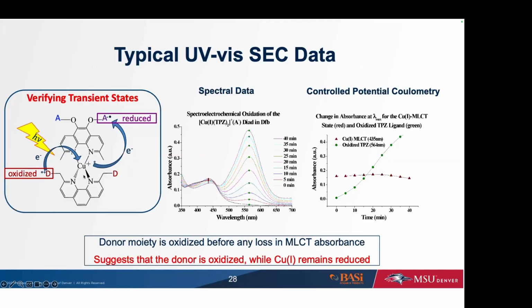So we were trying to determine with our spectroelectrochemistry, are we able to oxidize the donor before any loss of the metal to ligand charge transfer state, and to make sure that our copper is staying in the copper 1 state and not getting oxidized further to the copper 2, because that is what we needed for our setup to work appropriately. And so we were able to see this by watching the signal from our absorbance as we were oxidizing our donor, and we saw that before we had any oxidation of our copper, we got 2 of our donors oxidized, and that was stoichiometric with the actual complex.